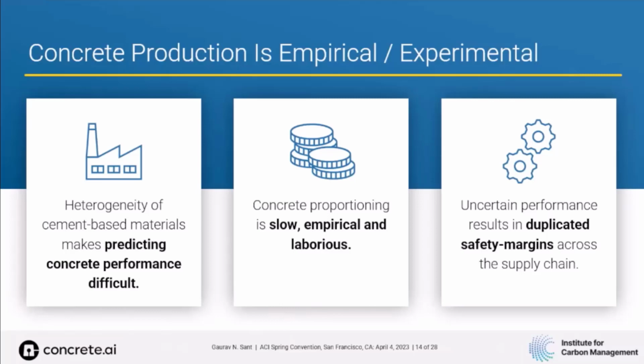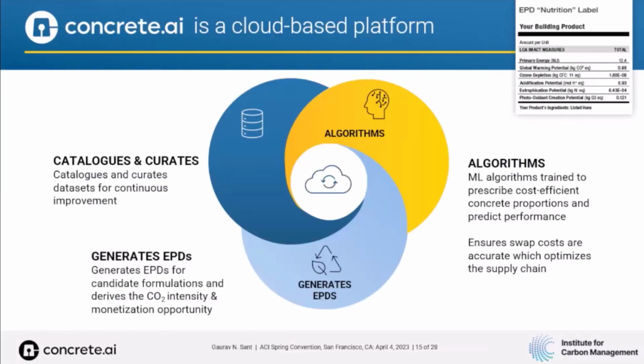Concrete proportioning is slow, empirical, and laborious. There's a mix design that's been sitting around. You're going to incrementally tweak it. Great. But it's slow. And uncertainty in performance results in duplicated safety margins, right? So the concrete producer adds some in, the structural engineer adds some in. And so you've got these replicated safety margins that come up. If you can start to pull these back, this turns out to be really important because you can start to reduce cement use by achieving better material efficiencies. So we did spin out a company that actually works in this area.